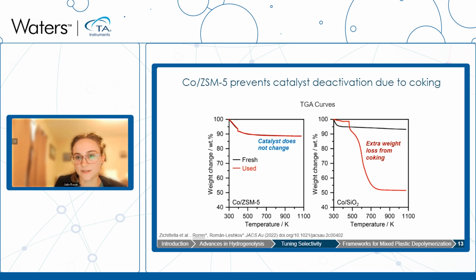Whereas if we support the cobalt on an inert support like silica, we see all this extra weight loss for the spent catalyst. And this is due to coking and coke formation that deactivates the catalyst on the surface.